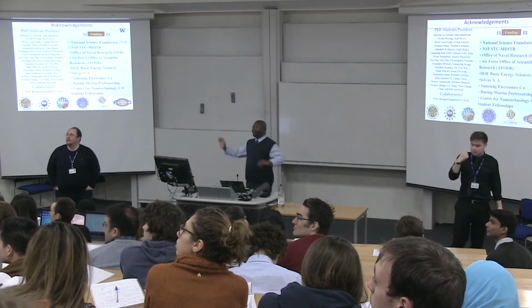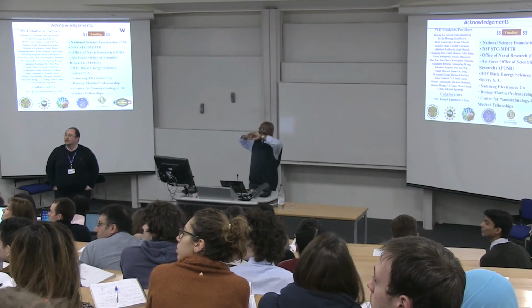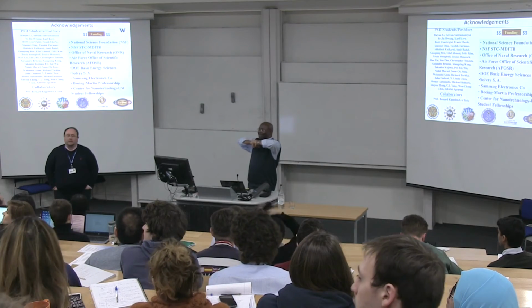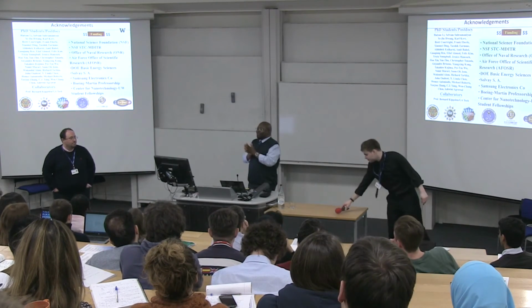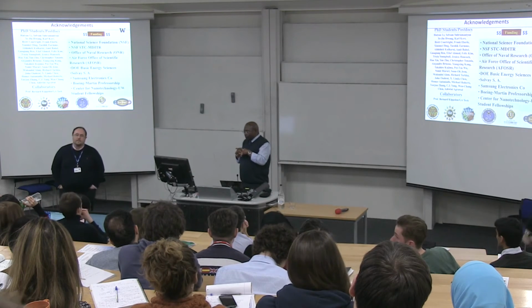One of the self-inflicted problems of sitting at the back is that I couldn't see what typical absorption lengths were for these materials. Well, yes. So the thicknesses of the films were typically 100 to 120 nanometers, and the absorption coefficients at the peaks typically 10 to the 5 per centimeter. So from that you can get the information you want.